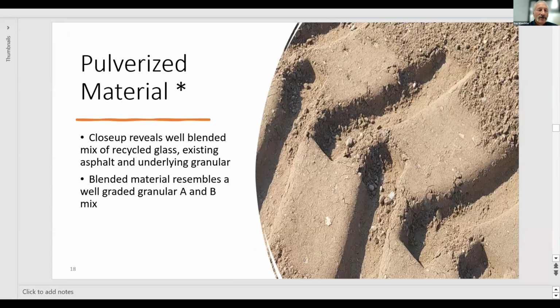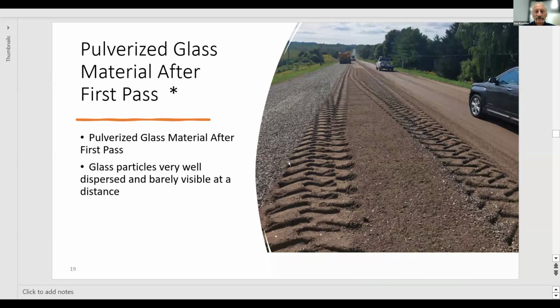Close-up revealed a well-blended mix of glass, existing asphalt, granular. The blended material resembled a well-graded granular A and B mix. So we're again very pleased with how this turned out. After the first pass, you can see the pulverized glass material, and the particles were very well dispersed and barely visible at a distance.